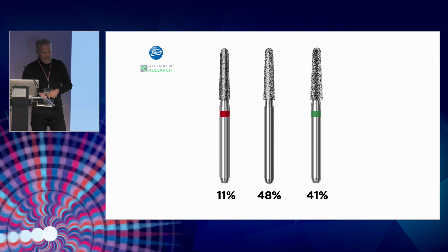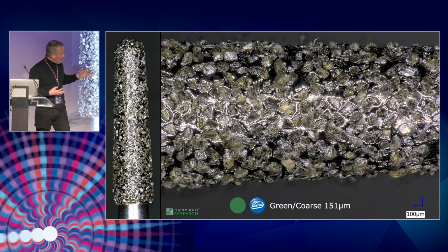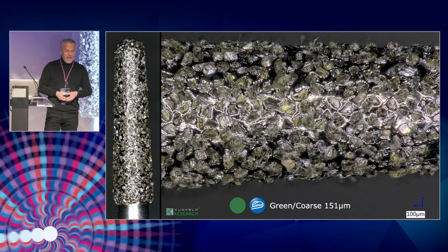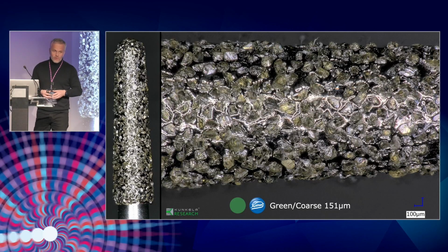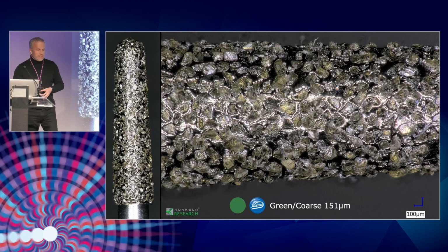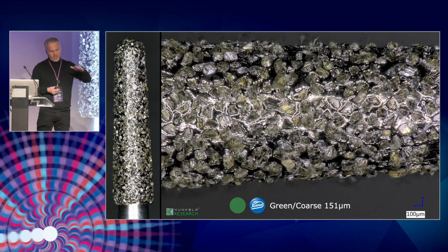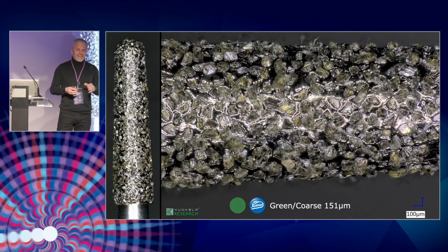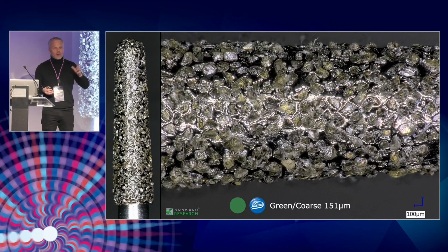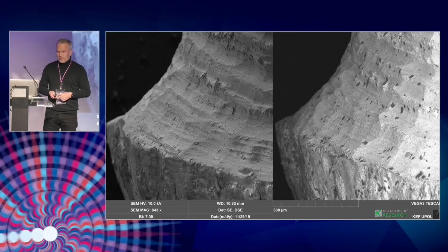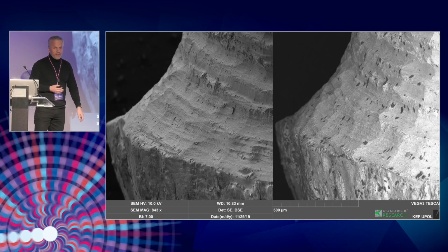The majority use the middle one, 48%, then the green stripe, and only 10-11% use the red stripe instrument. What we have to know is that the green coarse instrument has diamond particles of 150 microns on average. As you know, the recommendation from the FDA, the American Dental Association, or the Prosthetic Academy is that the gap between the restoration and the tooth preparation during dry fitting is between 20 and 120 microns. Once we use a diamond-coated instrument with 150 microns, we are over the gap recommendation. And this is how the tooth surface looks afterward. You can see how many chippings and invisible cracks there are inside.